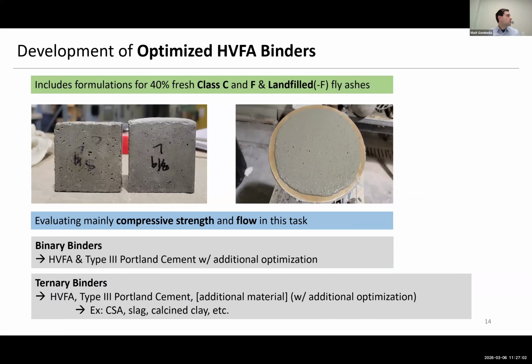All right, so what did we do? So the first thing that we did was develop what we called optimized binders. So we had increased from 25 to 40% fly ash, and we had looked at using a fresh class C and F and also a landfill ash from Pennsylvania, and different optimization strategies with the dosages, but also some gypsum optimization that I'll talk about in a little bit, and some admixture optimization.